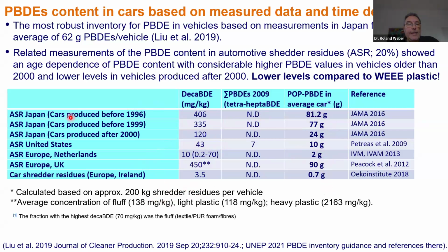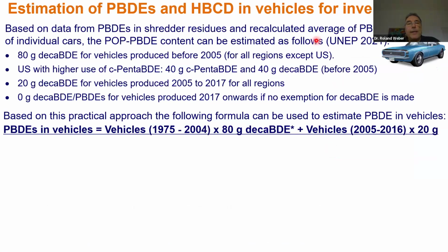What is interesting is that the cars produced before 1999 had around 80 gram per car, while cars produced after 2000 contain only 24 gram in the shredding. In other countries, here United States, only 10 gram. So you see that also for cars, what I showed you before for the electronics, that the DecaBDEs in these products are decreasing. Also this happened in the transport sector. This means cars after 2000 in average are lower contaminated. And this we have considered then for the proposed impact factors in the guidance.